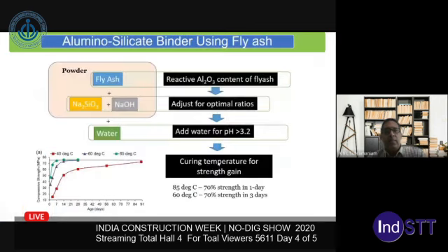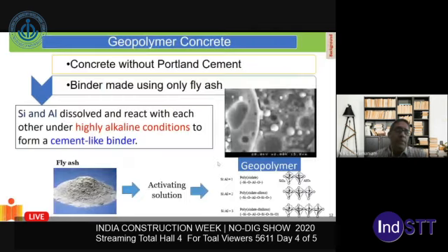Now, this geopolymer, if it is produced from alkali activation of fly ash, particularly the low calcium fly ash, tends to have a much higher strength than cement. It is much more durable, and it has very good fire resistance. So basically, it is an ideal material that can be used for construction. The only problem there is, of course, the temperature.